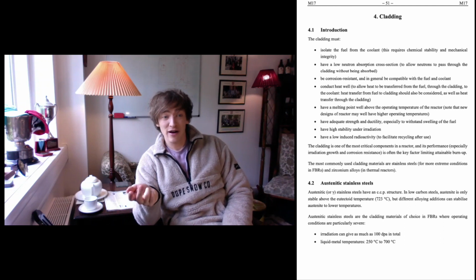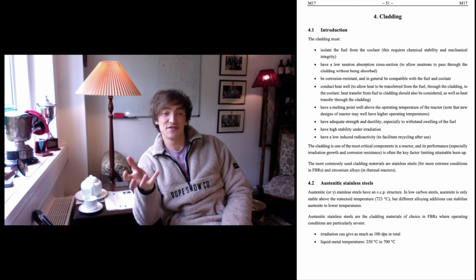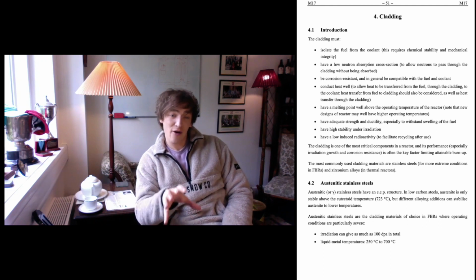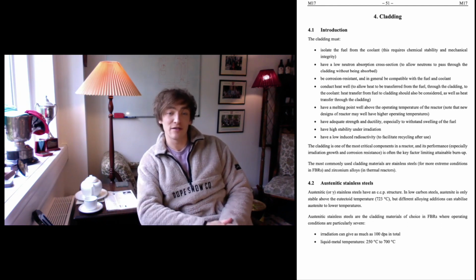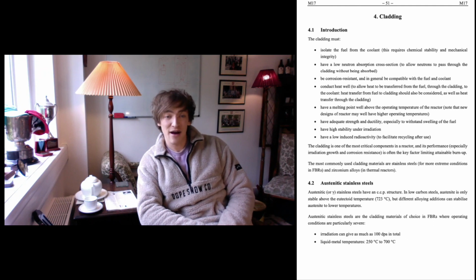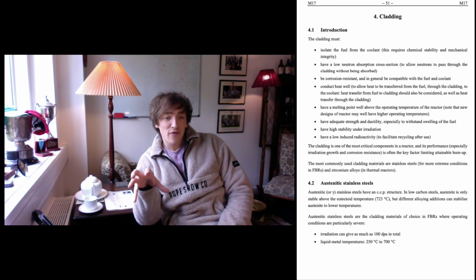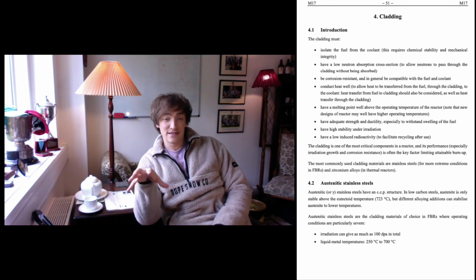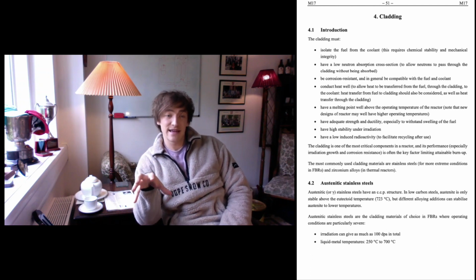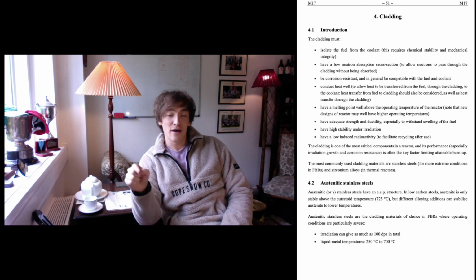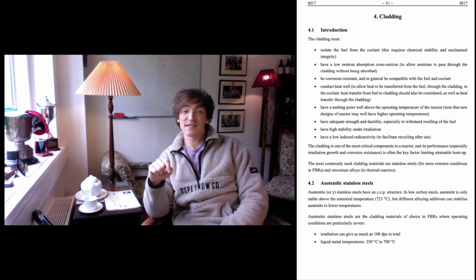Much like fuel, you've got to have pretty high stability under irradiation, and you've got to have a low induced radioactivity, because that's going to help you when you go to recycle your fuel and your cladding after you've used it. Now, improving the performance of cladding is critical, as it is often the cladding that limits attainable burnup. And as we'll see, there are a number of options for us to choose from, the first of which we're going to look at is austenitic stainless steels.